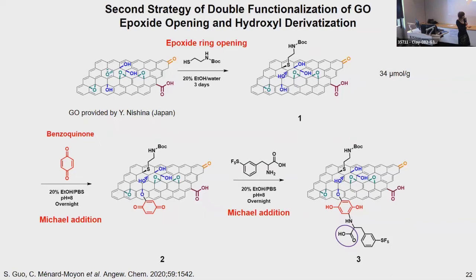And then this double bond was highly reactive towards an amine, and we used this phenylalanine derivative because, in fact, it has an SF5 moiety that could facilitate the characterization by FTIR and by XPS, as I will show in the next slide. And also, it has a carboxylic acid here that we can further exploit for derivatization with molecules of interest.